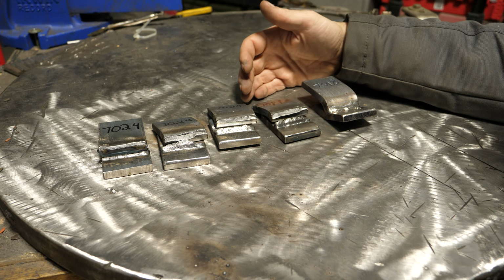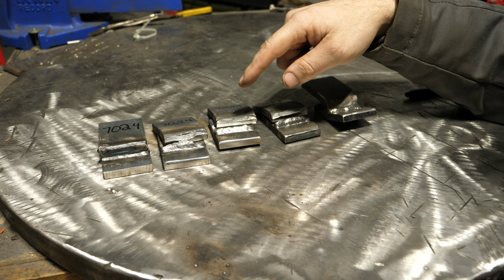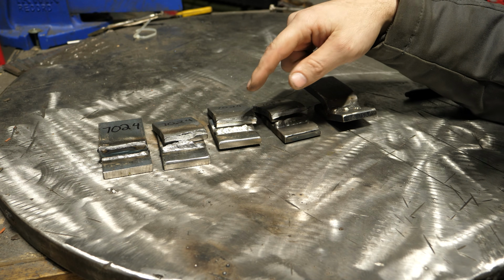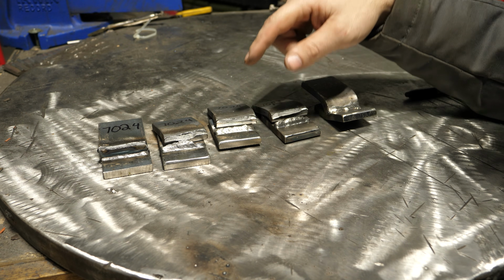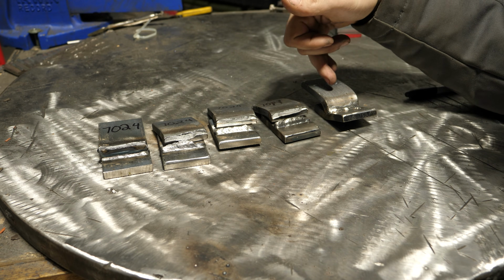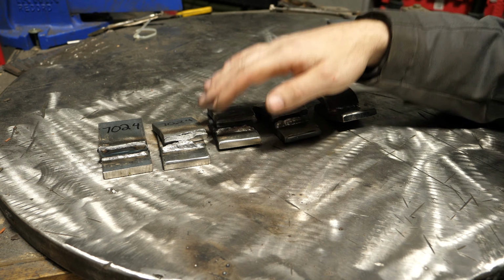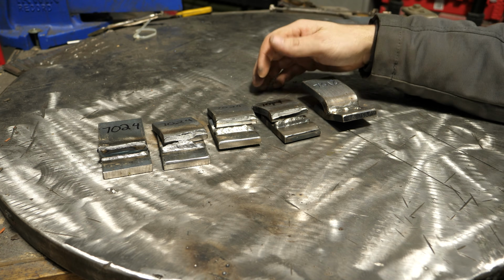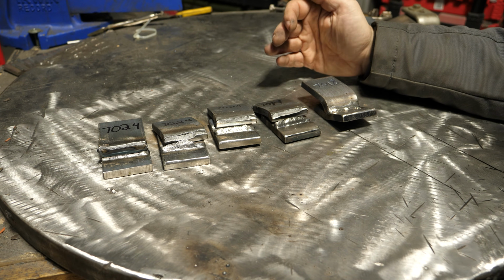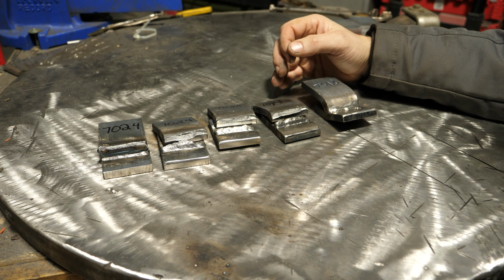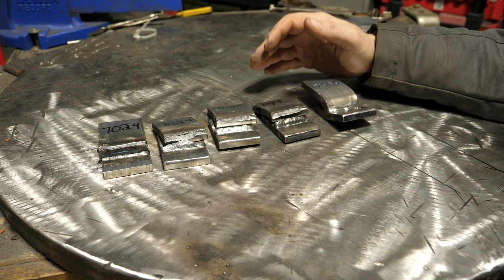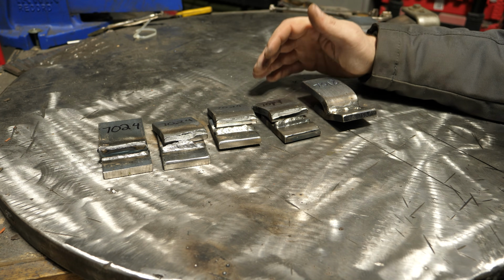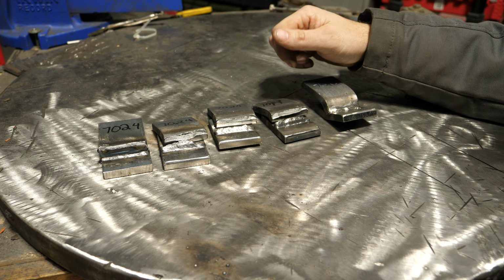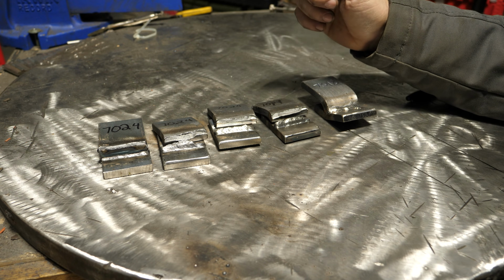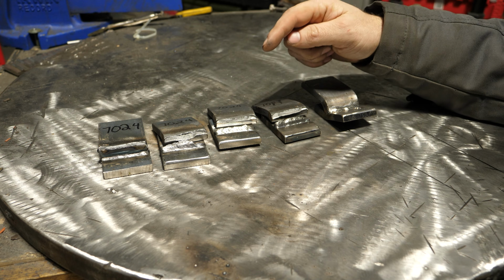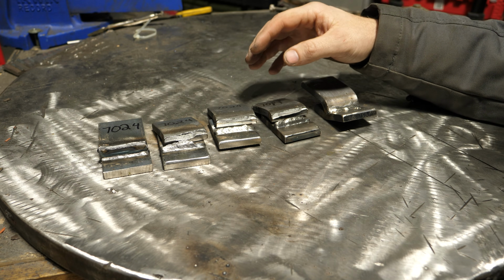The other possibility is that the 70-24 that I ran in this video simply does not have anywhere near the strength of the 70-18. And what I mean by that, this 70-24 is made by Blue Demon, okay? When I look up the specs for a Blue Demon rod like the 70-24, they list American Welding Society minimum specs as the spec for that rod. That means that it has to be 60,000 for yield strength and 70,000 for tensile strength.